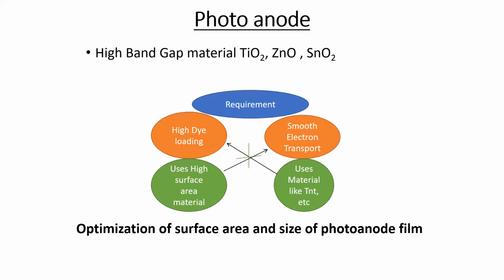Now there is some optimization. If we want smooth electron transport, then we have to use some nanotubes or some long height or long length material, not wavelength, I'm sorry. But this type of material will have very less surface area, and if surface area is less, we can't improve dye loading. And if we want high dye loading, then definitely we have to generate more surface area. But if you generate high surface area, then electron transport will not be smooth. So overall we have to compromise some effect, and we can get some optimum efficiency. These are the limitations.